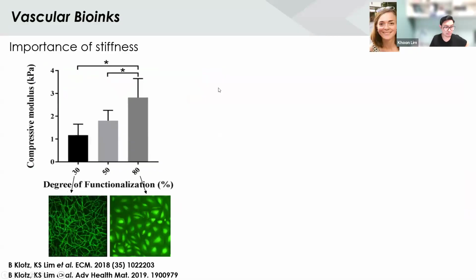When you think about bone though, a healthy bone is technically well vascularized. So how do we then control the bioink in terms of trying to get vascular supply to grow into them? If I want a bone implant to stay long and healthy, sustainable and viable, we need to make sure that you have healthy blood supply into them. What we did find, which was this work done by Barbara, is if you play around with your gelatin-based bioinks and the stiffness of it, we see that at a low stiffness, the vascular cells or the endothelial cells are able to form microcapillaries.